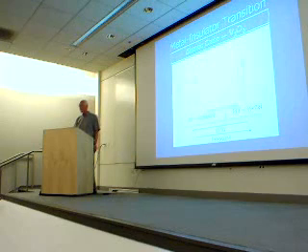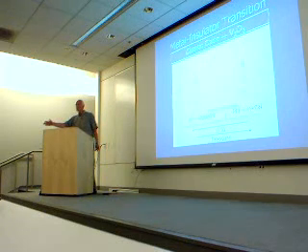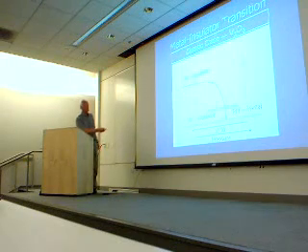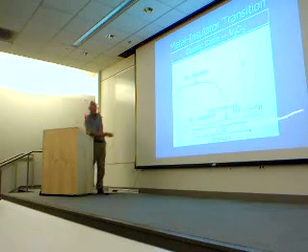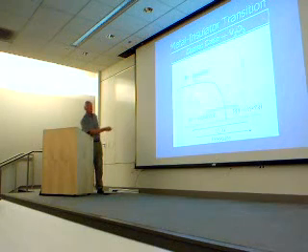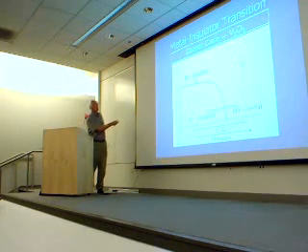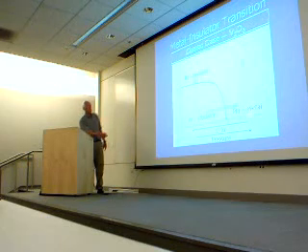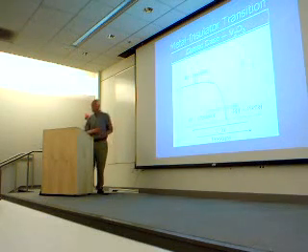If you go up starting with the antiferromagnetic insulating state, you do expect something to happen. What? Transition to a disordered state, right? And basically, you know from theory of phase transitions that you've got to have some kind of a curve that's like this. That would be a decreasing transition temperature, say with pressure, or as U decreases, right? And now I've written up here paramagnetic insulator because that is what you find in the vanadium dioxide. It's not guaranteed that this is what will always happen. But notice that now we have this metal and insulator.